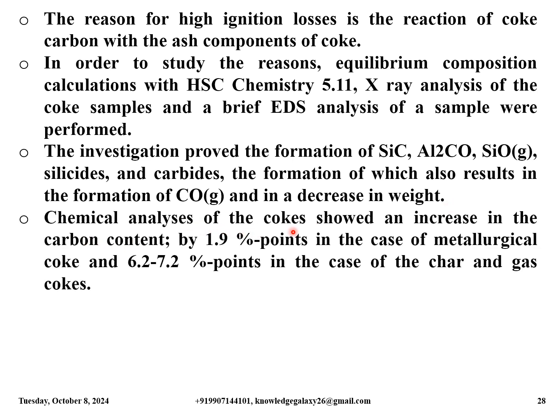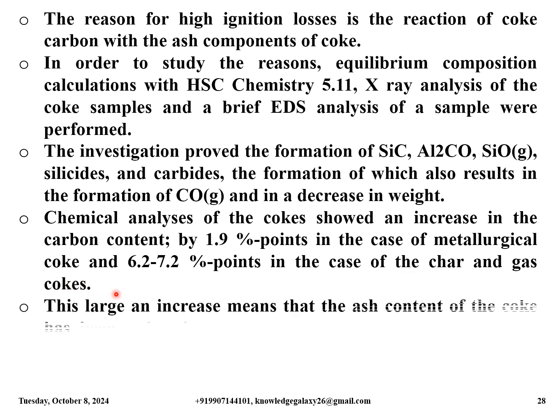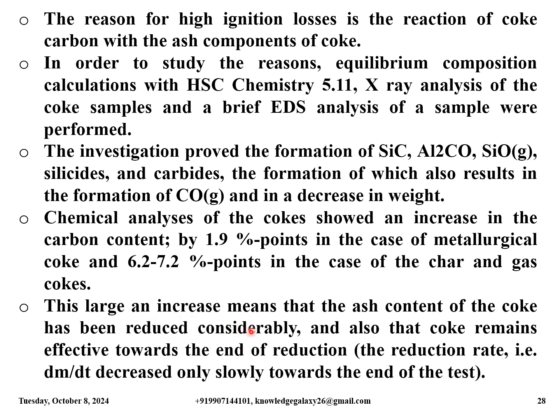Chemical analysis of the cokes showed an increase in the carbon content by 1.9 percentage points in the case of metallurgical coke and 6.2 to 7.2 percentage points in case of char and gas coke. This large increase means that the ash content of the coke has been reduced considerably, and also that coke remains effective towards the end of reduction. The reduction rate, that is dm by dt, decreased only slowly towards the end of the test.